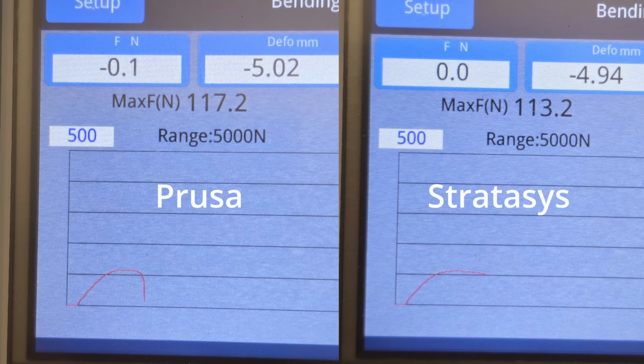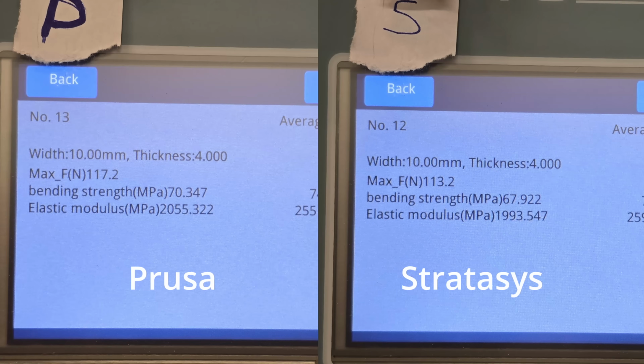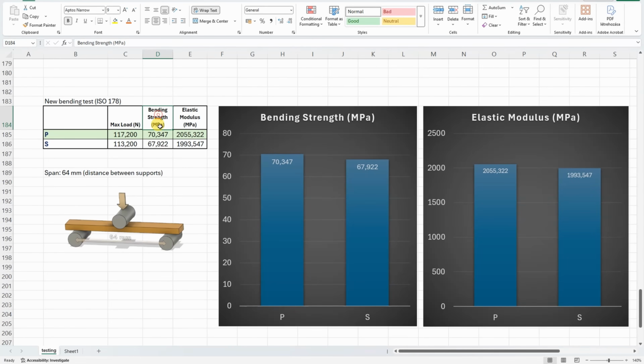Here you can see the graph, and here the maximal force, bending strength and elastic modulus. The bending strength is calculated from the maximal load, so that's why only the bending strength is presented on the graph, because the ratio is the same, and we can see very small advantage on the side of the Prusament. Elastic modulus depends on the deformation too, and again the Prusament was just a little bit better compared to Stratasys, but the difference is not big in this case.